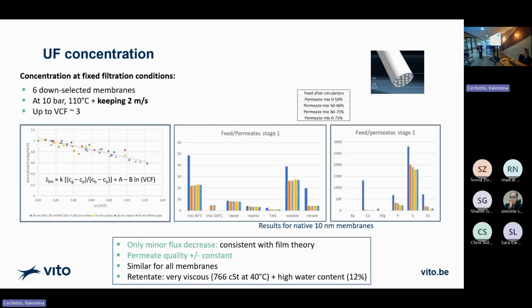When we look at the other graphs, at the permeate quality, we picked the permeate samples, of course, at different moments of concentration. We went all the way up to about 70% recovery, which is the maximum here. And we see that the permeate quality stays nicely constant. And it's similar for all membranes. Also good to see is that the retentate that you create is then a very viscous thing.